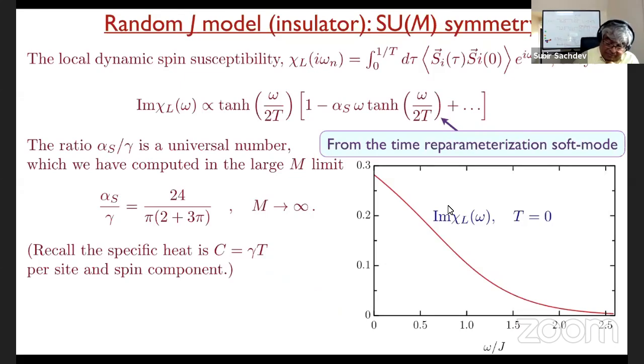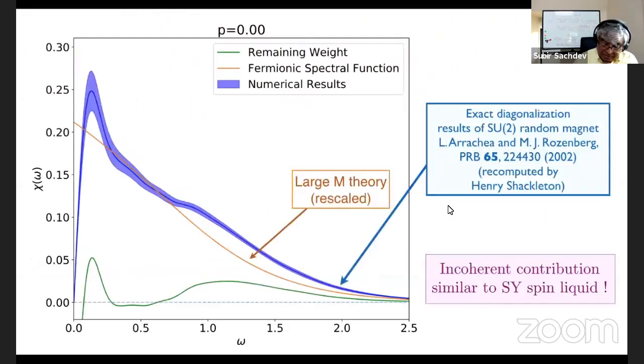Okay, so now I also want to talk about some recent work by Henry Shackleton and others, and I'll show that work in more detail later when we get to the doped system. But in this case, this work is reproducing earlier work by Arrachea and Rozenberg. So what they did was just take an exact diagonalization of the J model for SU(2). And in that model, after averaging over many sites over some cluster of 20, 30 spins, you can compute chi of omega. So the blue line here is the result from exact diagonalization.